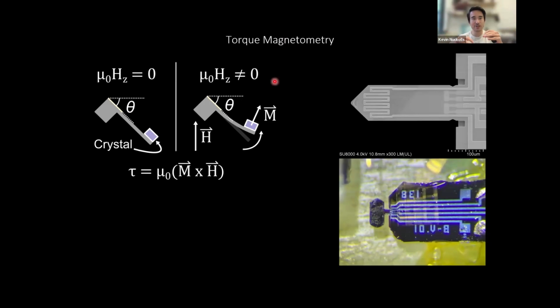So a brief refresher, torque magnetometry works where I have a single crystal that I affix to the end of a silicon nitride cantilever, and I place this thing into a magnetic field. And if this crystal is isotropic, then in linear response to the magnetic field, the magnetization of this crystal will point directly into the magnetic field's direction. And so this crystal will feel nothing. But if this crystal is anisotropic in any way, like it has an out-of-plane and in-plane magnetic susceptibility that are different, then this crystal's magnetization will not point in the magnetic field direction. And so this crystal will feel a torque, tau, which looks like the magnetization crossed into the magnetic field, which will try to deflect the crystal into the magnetic field, into a lower energy configuration.